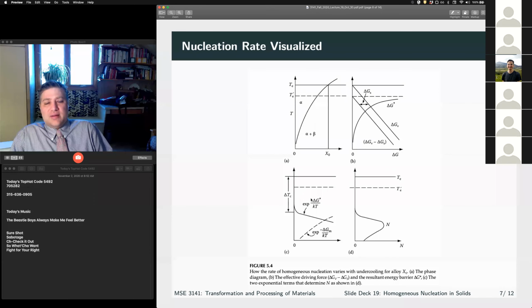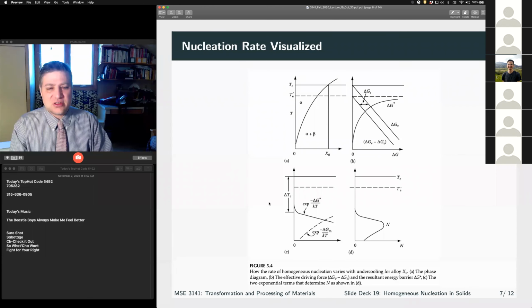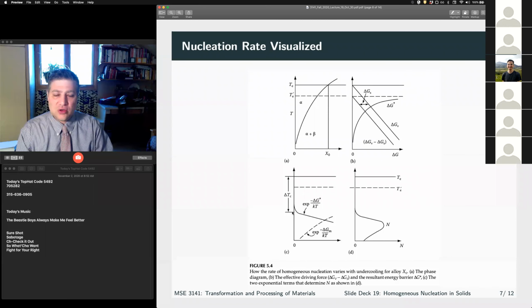But there's going to likely be some temperature where these cross, right? And in which case we get a peak, a maximal nucleation rate. Our nucleation rate increases and then decreases, right? This is different than our nucleation rate for solidification, which just kept going up, right? It was like a step function. We hit our critical undercooling and boom, we got a huge spike in nucleation rate. Here, we have to take into account our mobility. So we get an increase in the nucleation rate at some critical undercooling that reaches a maximum and then decreases down to zero, right?